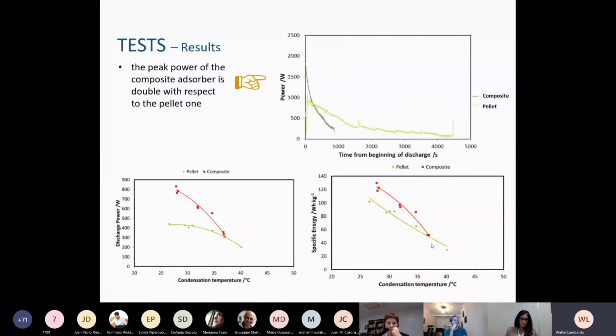About the two absorbers, the composite and the pelletized absorber, the results show a comparison of these two different types. We can see in the first diagram the power versus the time. For the composite, we can see an initial peak power that is 2 times the pellet one, but the process is very quick. It ends at more or less 1,000 seconds, while the pellet one is more constant, and it ends at about 4,500 seconds.